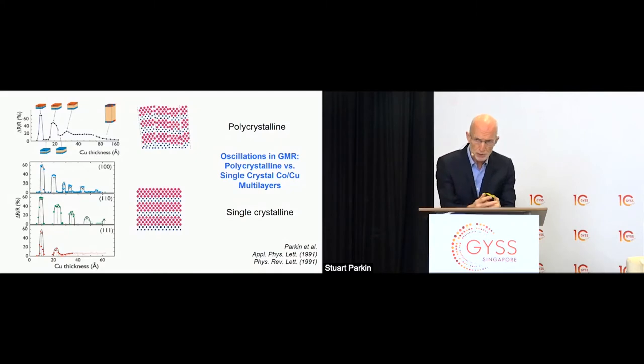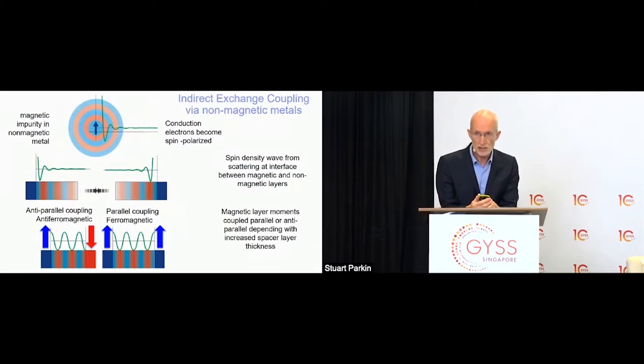As I said, these are all at room temperature, so it makes these effects super interesting and useful. And just to explain briefly what gives rise to this magnetic long-range oscillatory coupling is a spin polarization of the electron gas in the system. So as shown in this cartoon, if you introduce a magnetic spin into a non-magnetic metallic host, then the electrons will try to screen that magnetic impurity. But because it's magnetic, the response itself is spin polarized. And the spin polarization of that electron gas can then lead to a long-range magnetic coupling.